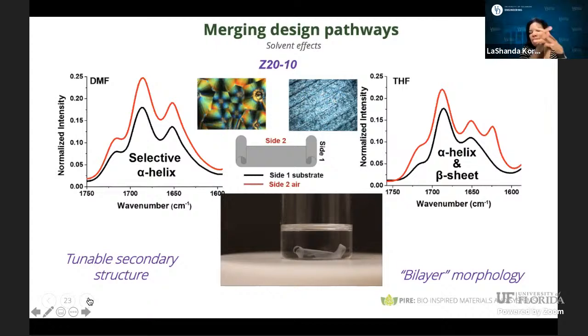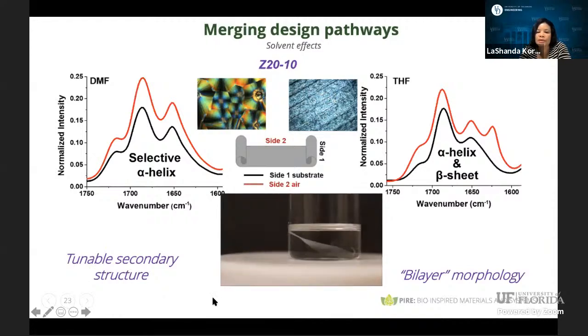However, if you use THF, you actually have one system. One side of the film forms a mixture of alpha helix and beta sheets, whereas the other one is primarily the beta sheet structures. And with that, you generate a bilayer morphology. And what does that give you? When you expose this system, which has a mixture on different sides, you actually are able to generate actuating material. It curls up into a really nice spiral structure, all driven by the fact that you can use solvent to self-select each side of the film.